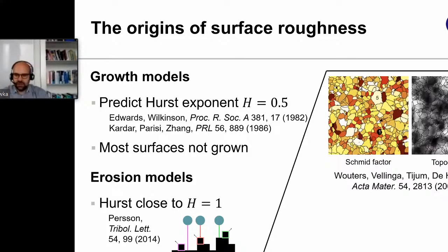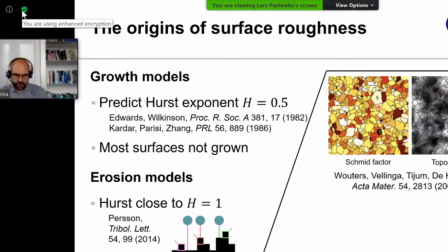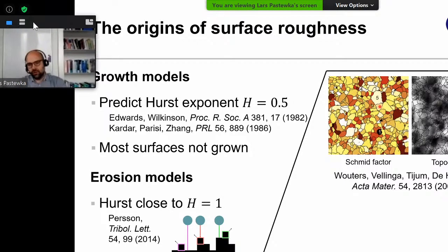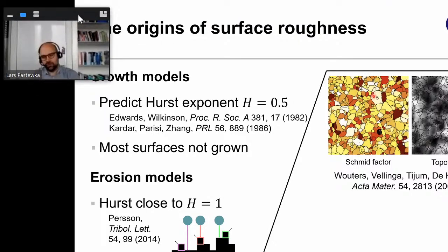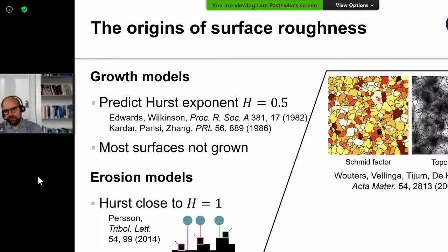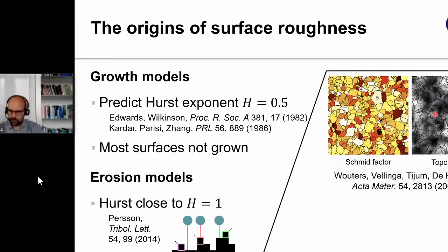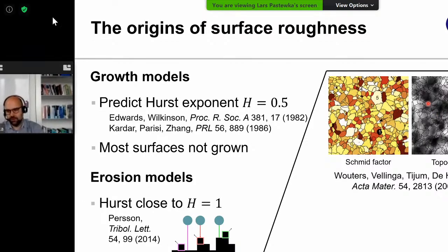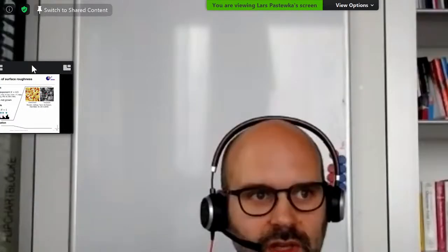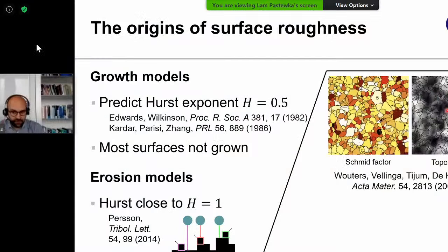So why would deformation lead to surface roughness? So the very traditional view of how roughness emerges, in this case in a polycrystalline metal, is imagine you have a microstructure such as the one shown on the top right here, where the color indicates essentially grain orientation. In this case, it's a Schmid factor, which tells us how the grains deform. And let's assume that the grain orientation is different. So some of these grains deform easily to some sort of applied load, and others are more resistant. Then of course this will lead at a surface to the evolution of a topography. And this is what's shown in this red image here on the right. I will show you later that we think that this doesn't give rise to self-affine surface structure, while it gives rise to, of course, surface roughness.